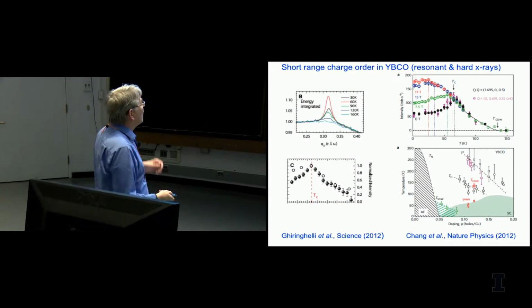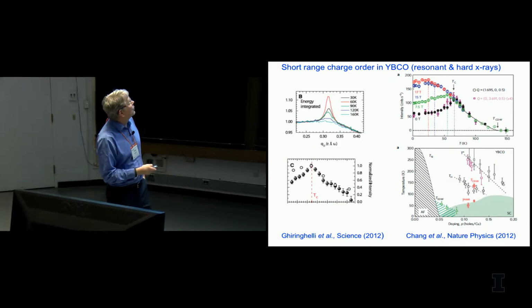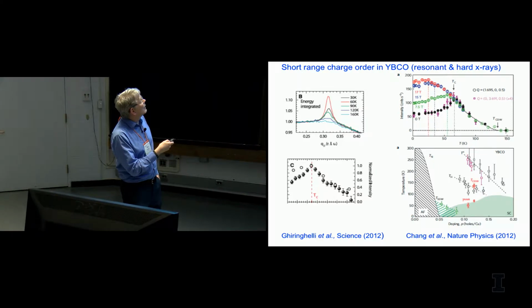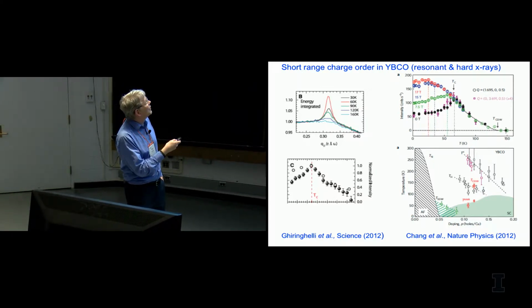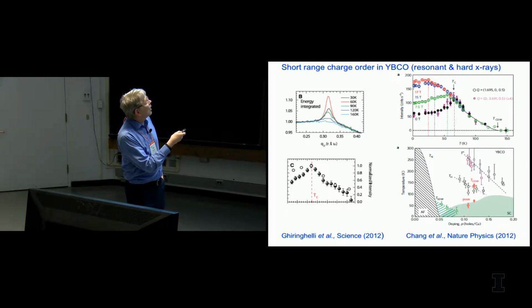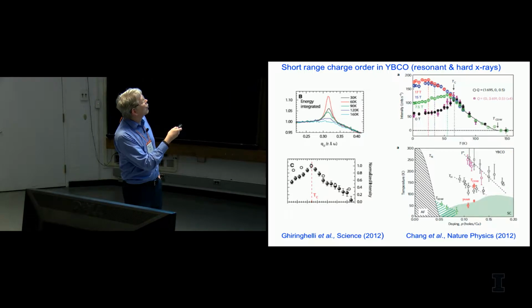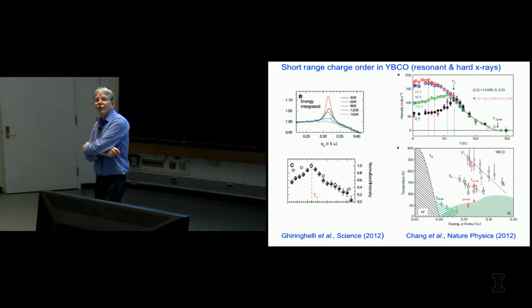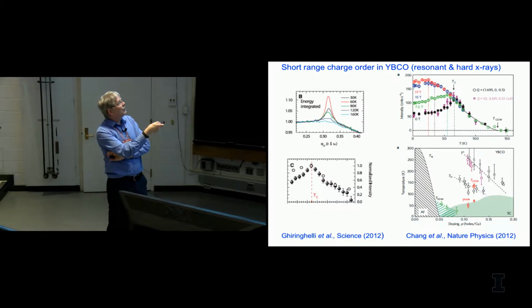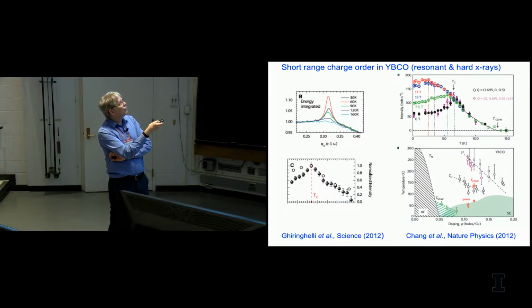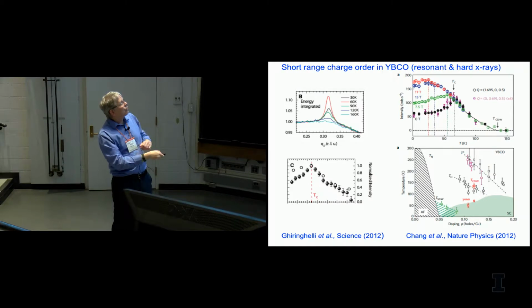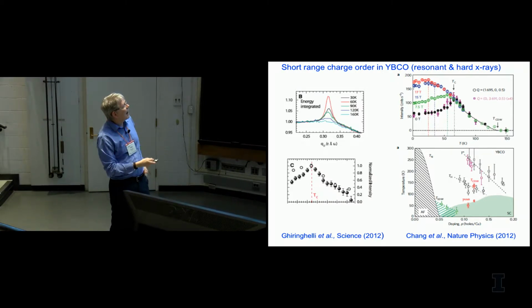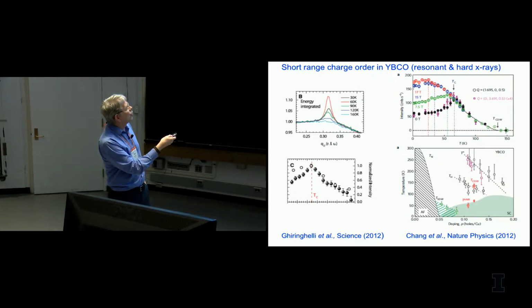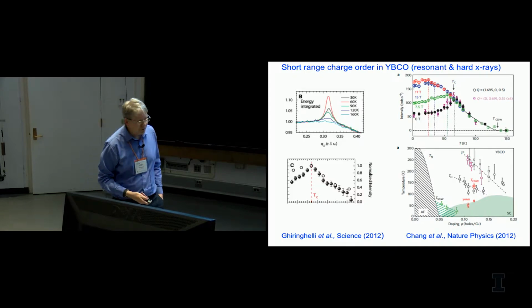Then, about 5 years ago or so, people started doing both resonant and hard X-ray scattering, and an effect that had been missed for a long time was seen that as you go below some temperature, below T star, but still well above Tc, you start to see charge correlations develop that look like they're going to diverge as you go to the zero temperature limit, but then when you hit Tc, they get suppressed. Of course, if you go up in a magnetic field, and suppress superconductivity, then these charge correlations come back. And this is some sort of short-range ordered phase that more or less sets in at a temperature well below T star, but well above Tc.